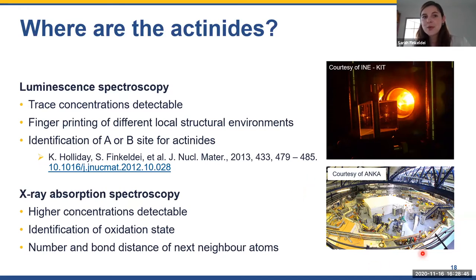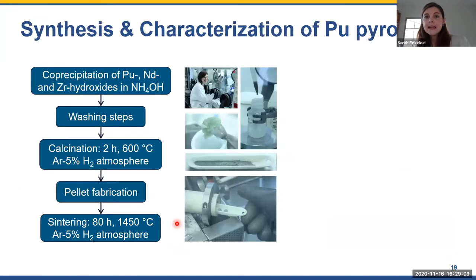And for those ones, we have used another characterization technique, which is X-ray absorption spectroscopy, where you can detect higher concentrations, where you can identify the oxidation state of your element of interest, and also get information about the number and bond distance of next neighbor atoms. So what I did is I went for quite a while to the Netherlands, to NRG, and developed a synthesis route there to fabricate a plutonium pyrochlore. So this was, I think, the day I succeeded in fabricating the pyrochlore, so that's why I look so happy. We did a co-precipitation and performed all temperature or thermal treatments under reducing atmospheres.